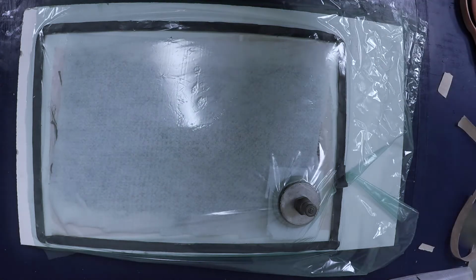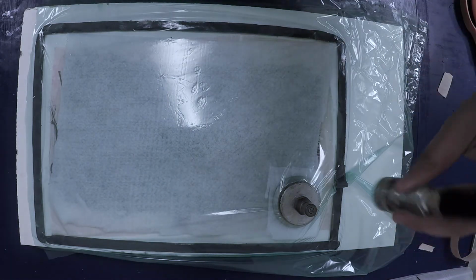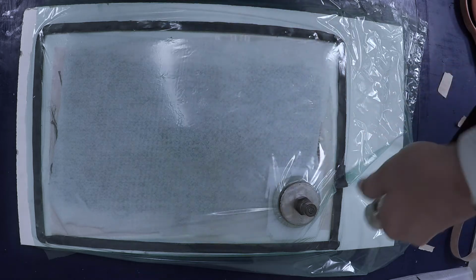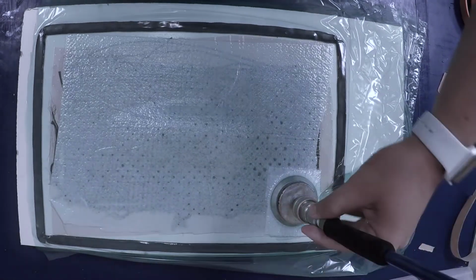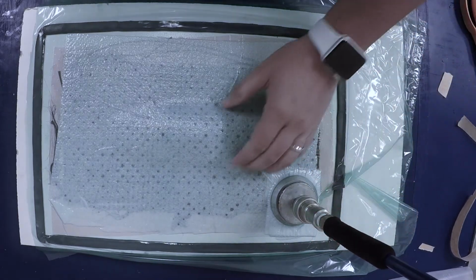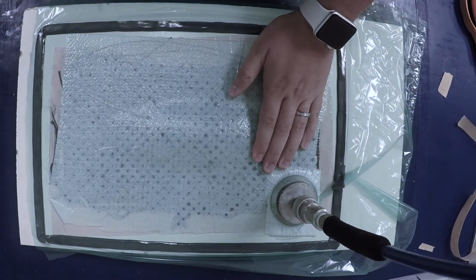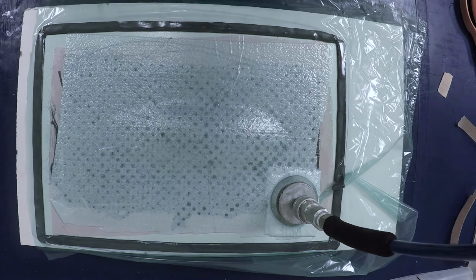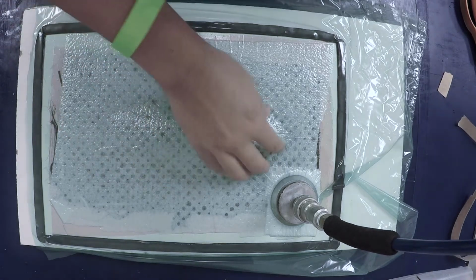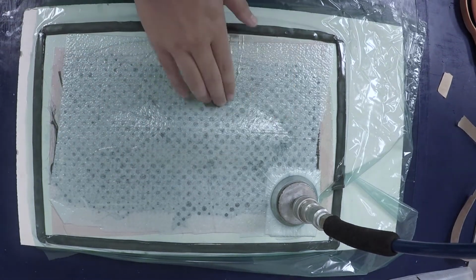You are now ready to connect the vacuum to your mold. Do this by pulling the quick release handle from the hose and connect it to your mold. As you can see, the vacuum pressure pulls the fabrics down tightly over the mold. The resin begins to travel through the release film and begins soaking the bleeder.